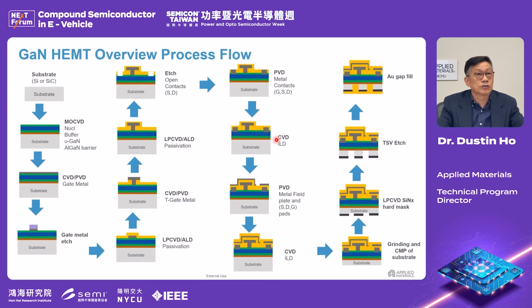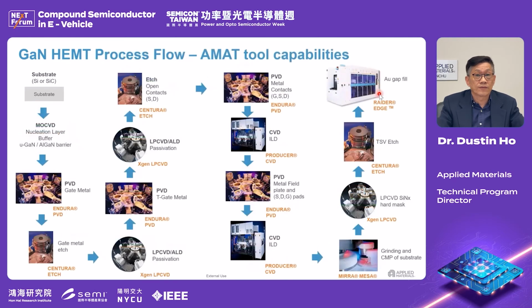Then metallization. Then you have the CVD, PECVD for the ILD, then the PVD for the field plate and source drain pad, then the PECVD ILD. Then you need grinding, CMP substrate, and then you have the nitride hard mask. Then for the IF, you have the backside TSV etch and the backside metallization, the gold gap fill.